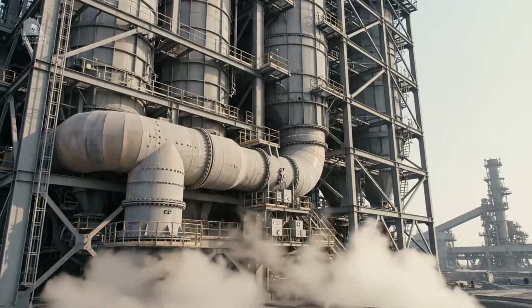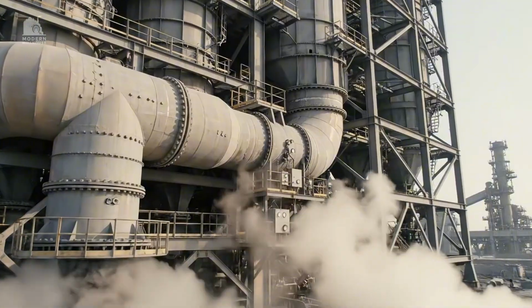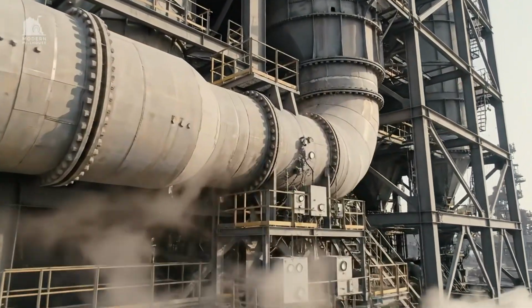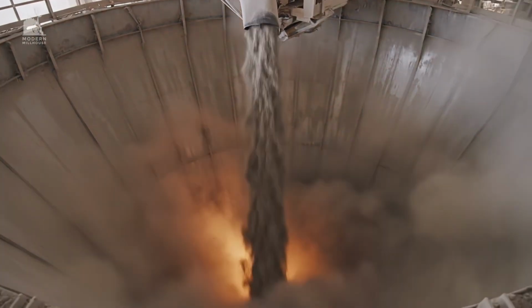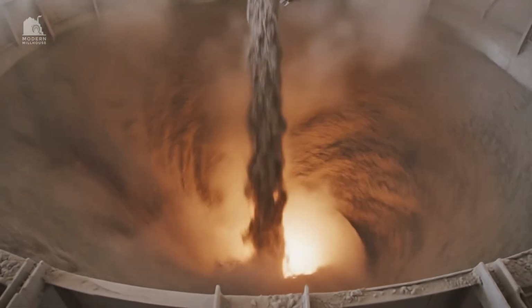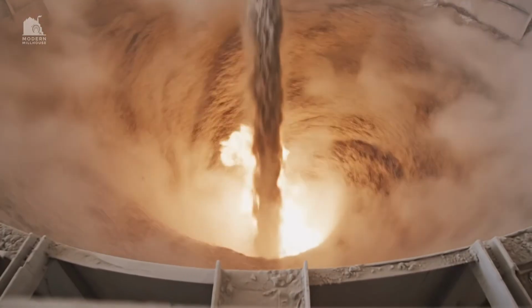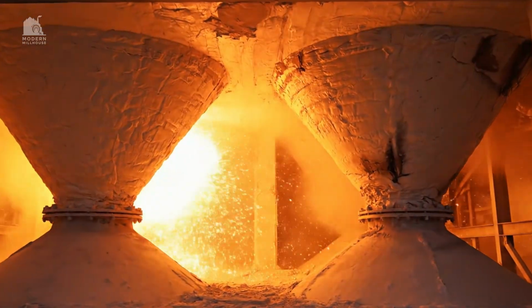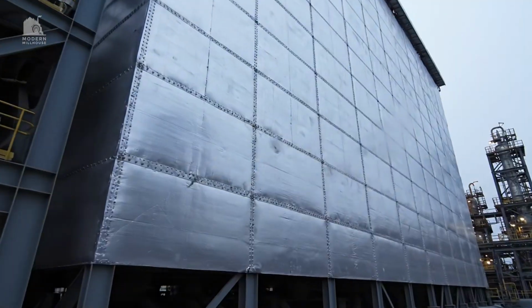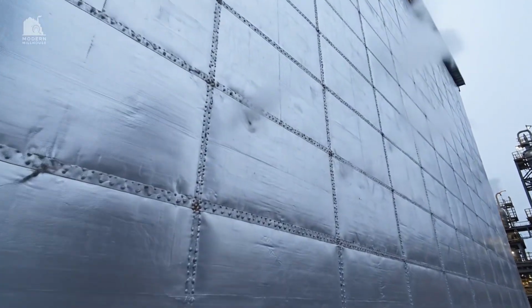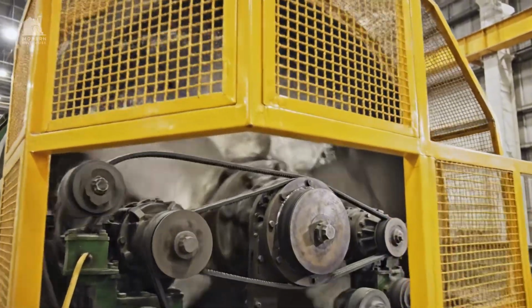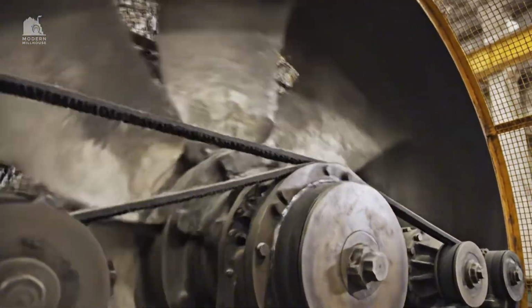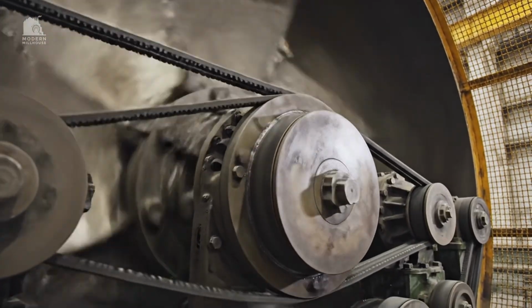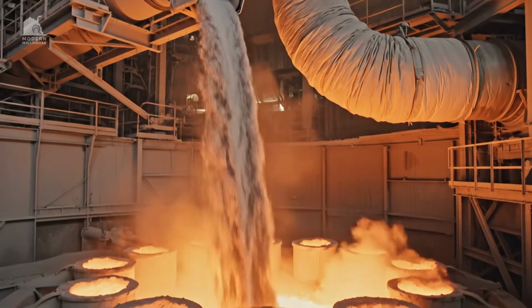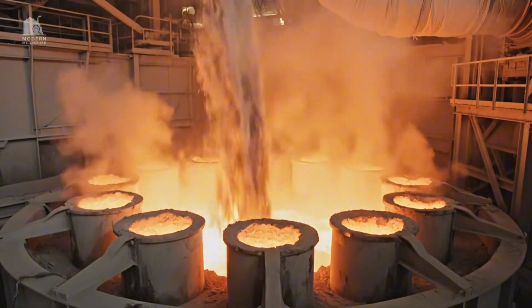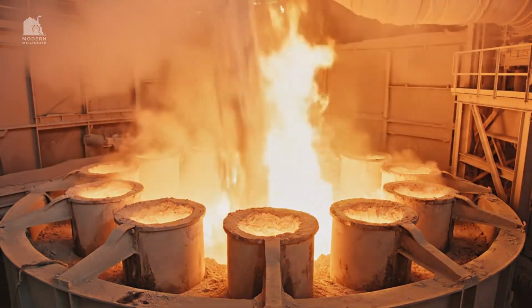The preheater is essentially a vertical heat exchanger, designed to extract maximum value from kiln exhaust gas. As raw meal meets rising hot gas, it heats in seconds, beginning the thermal journey toward calcination. Heat management is critical, so refractory and insulation protect steel structures while keeping energy inside the process. Large fans drive the entire gas flow through cyclones, mills, and filters, making airflow control a core skill in cement making. Next, the calciner begins the key chemical break, turning limestone into lime and releasing the first major CO₂.